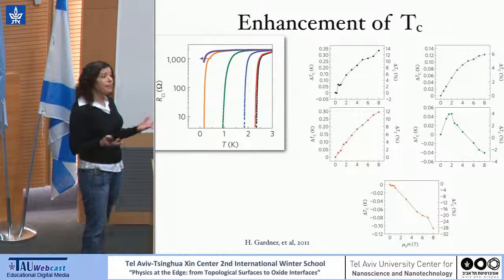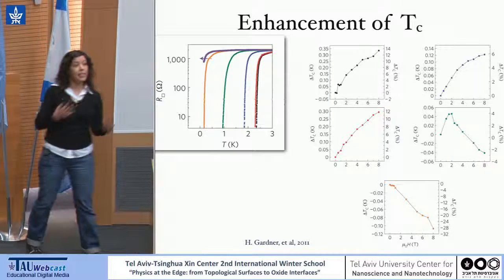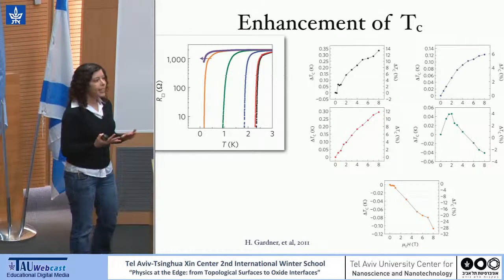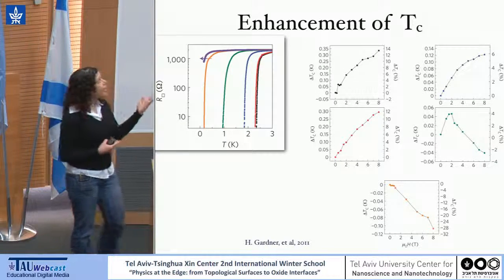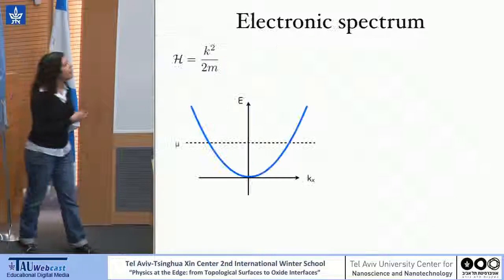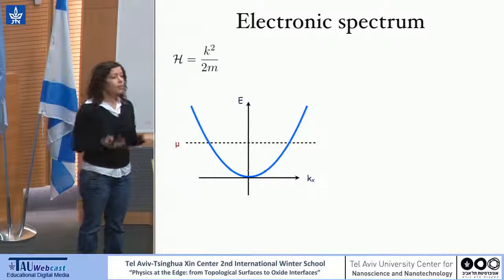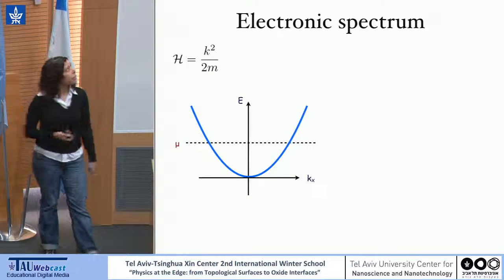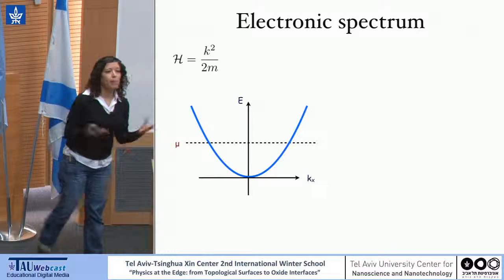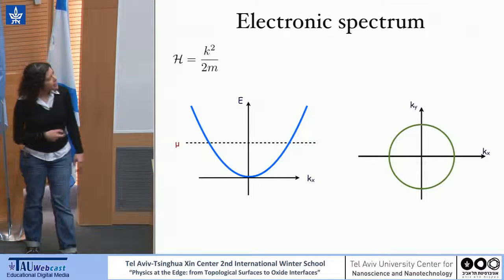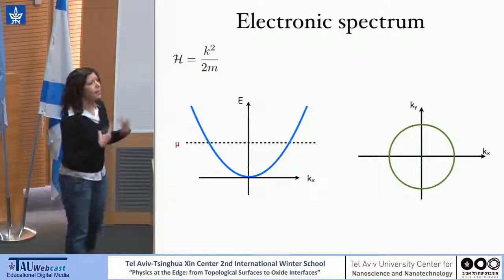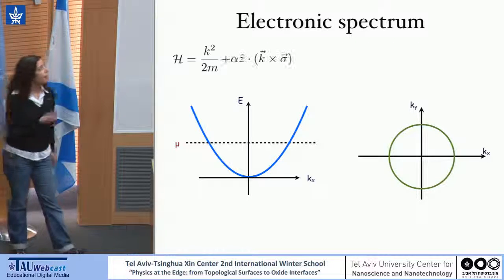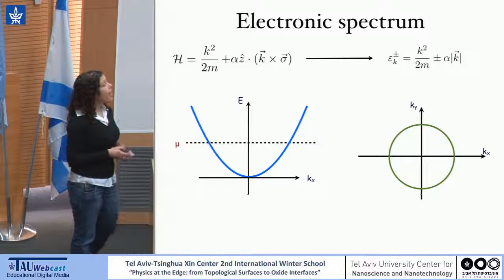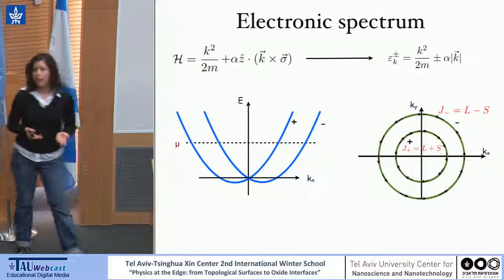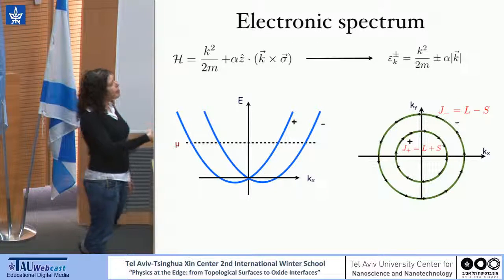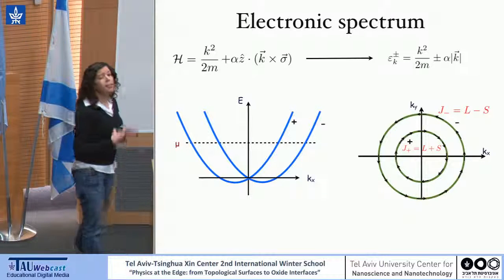Okay, so we have two puzzles, and one is why we see the growth in the critical magnetic field as a function of spin-orbit coupling, and the second is why TC grows. So let's look at a generic model for an electronic system with spin-orbit coupling. First I will look at just a parabolic band, and that will be our Fermi surface. In the presence of this parabolic band, it will be doubly degenerate because of spin. I'm adding spin-orbit coupling, and the effect will be to split the electronic spectrum, to split the Fermi energy, and we have two bands where basically the direction of the spin is coupled to the momentum of the system.